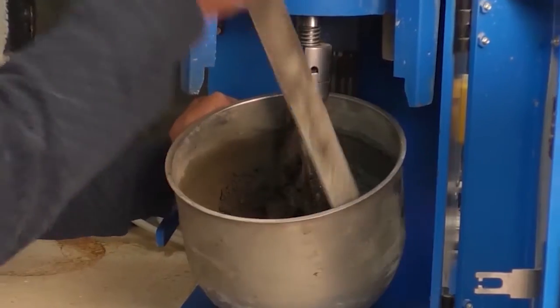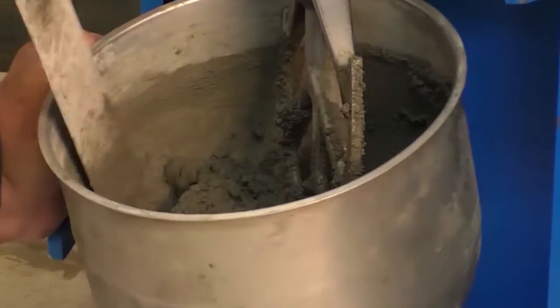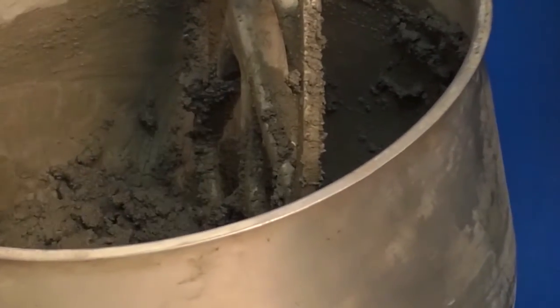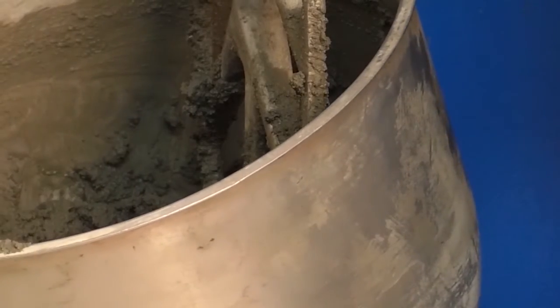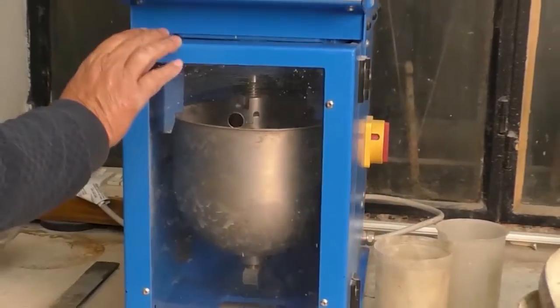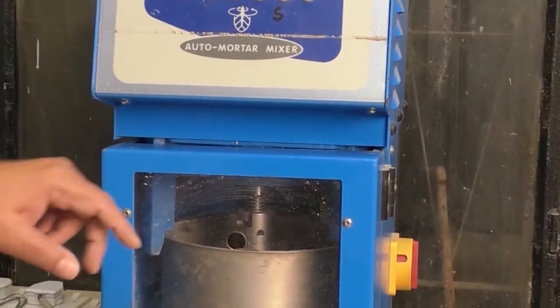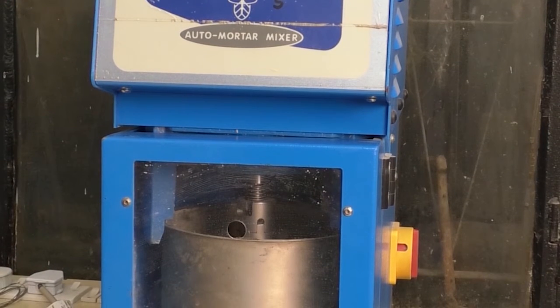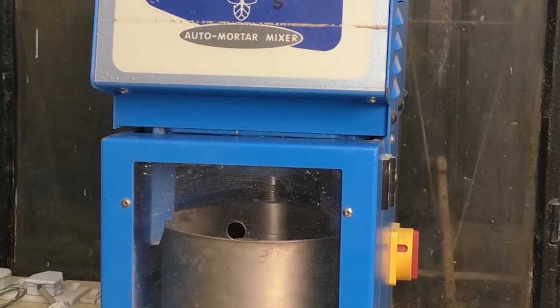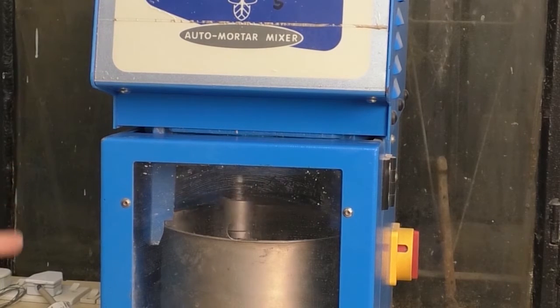During the first 15 seconds of this interval, we have to quickly scrape down any mortar that may have collected on the side of the bowl. After the 90 seconds of rest, we have to finish the mixing within 1 minute by rotating it at medium speed.